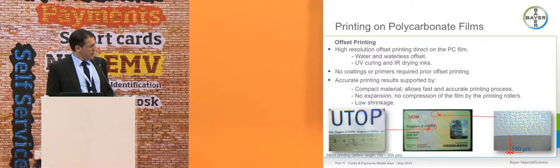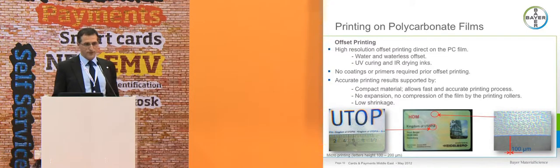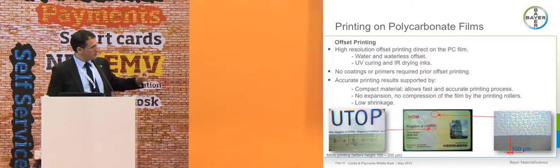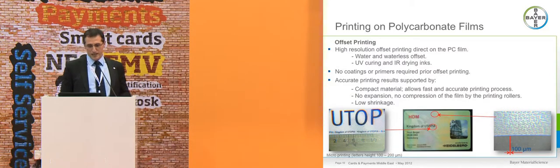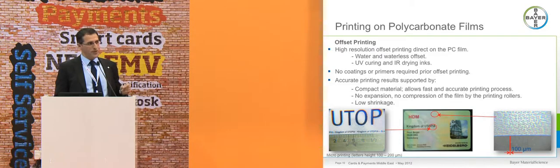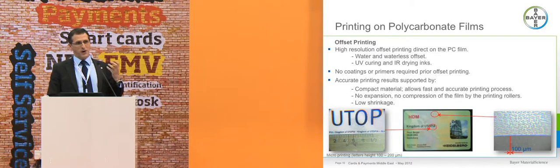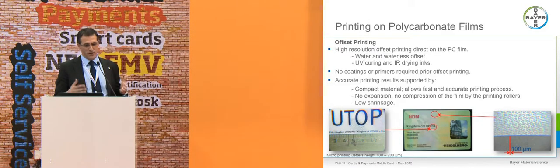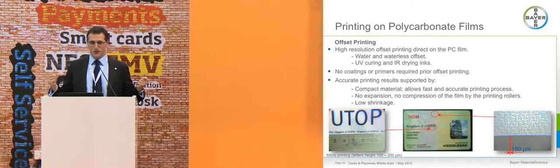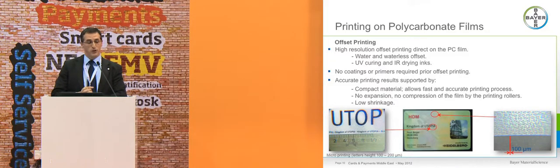You can see down there some magnified pictures from the surface of such a document. You see micro printing is possible in a higher resolution without any problems. Furthermore, because polycarbonate is a quite stiff material, you can print it in an easy way without any kind of expansion or contraction of the material, which would make your life difficult during the printing process.